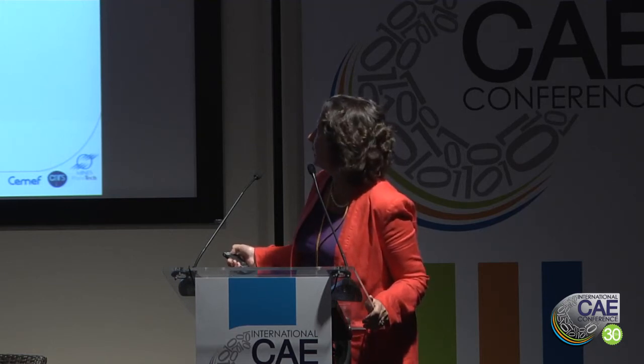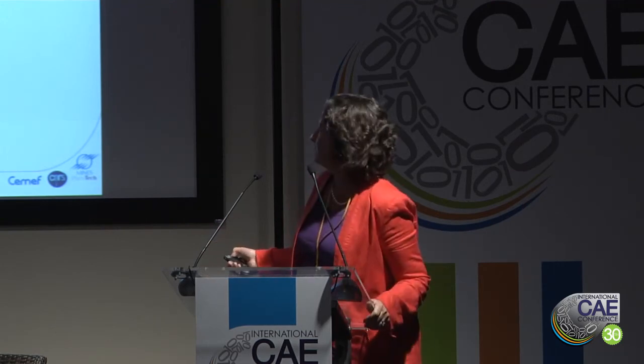So the evolution of the grain is based on a very simple kinematics equation here, the velocity. Here you have the boundary mobility. Here you have the term in terms of curvature of the grain, in which we can have boundary energy, grain size, and Zener pinning. This is a metallurgical keyword. And here we have the stored energy, and here is the external normal at the surface of the grain.